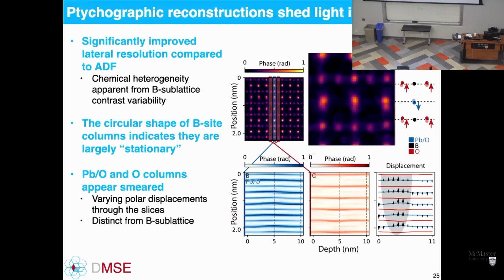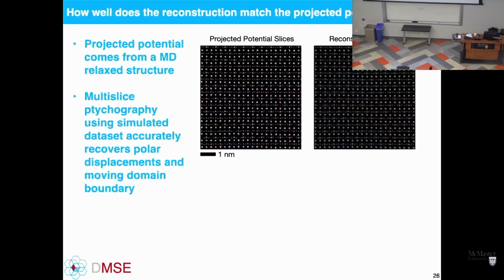And so these types of information are really the 3-dimensional displacements being able to be extracted through the depth. Now, how well does this actually line up with what, from theory, we would expect to be the case? And for ptychography, we can simulate a structure using molecular dynamics to get the polar displacements as a function of position, and then simulate a 4D STEM data set, and then reconstruct it.